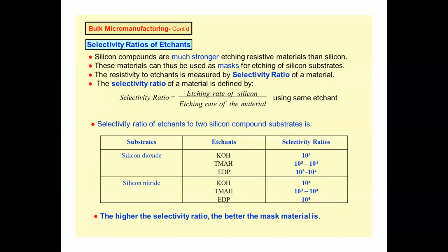And there is a selectivity ratio, that is the etching rate of silicon and the etching rate of the material used by the same etchant. That is why sometimes it happens that a particular material is bought from a company or a vendor, and you standardize the etchant, and next time you get the chemical from a different vendor, you may have to standardize it again, because the purity of the material, the molarity of the material, etc., may vary from vendor to vendor. So even though there is standard data, as a designer or as a researcher, one has to always standardize or calibrate these processes before actually realizing the structure.